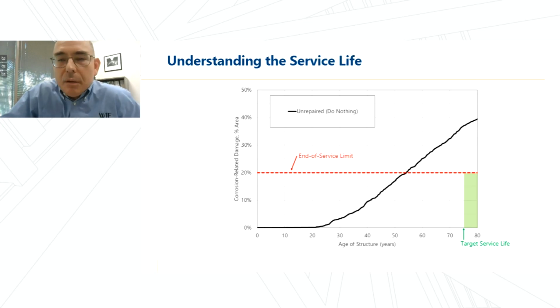Let's take a few minutes to talk about what an expected service life for a structure might look like. This graph depicts the service life of a hypothetical reinforced concrete structure whose functionality is controlled by corrosion-related damage. And you can see on the vertical axis on the left, it's showing the percentage of surface area that's affected by corrosion-related damage. And there's an end of service limit that's been established at 20%, shown by the red dashed line. And that is for this generic example.